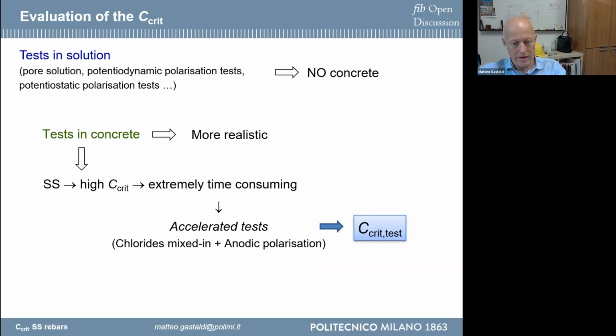When you make this test, you have an indication of a chloride threshold that is not the real chloride threshold, but the chloride threshold related to the test. Then you have to use coefficients that help you move from the test chloride threshold to the real critical chloride threshold. For example, the result that Professor Merkes showed before is fantastic, because if we have a result from a real structure, we can use it to obtain the coefficient that allows this comparison between the chloride threshold in the test and in the real structure.